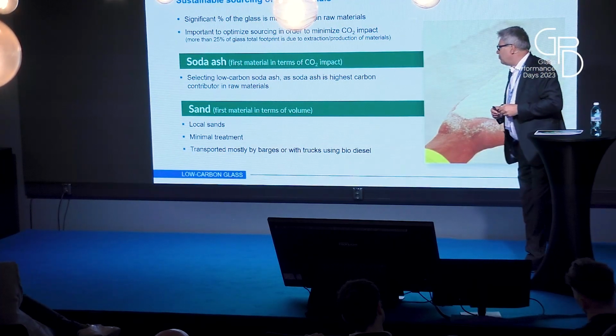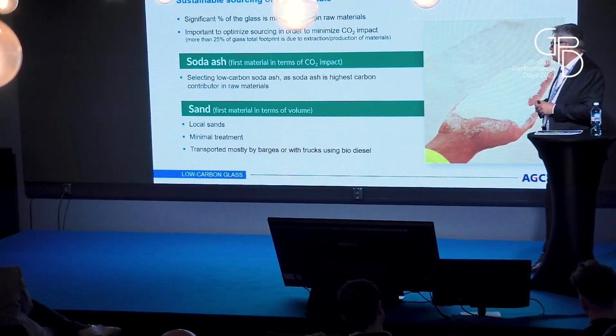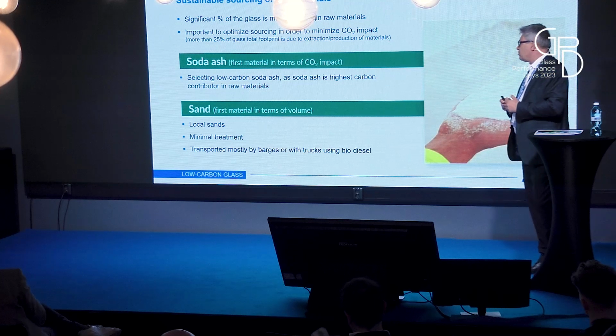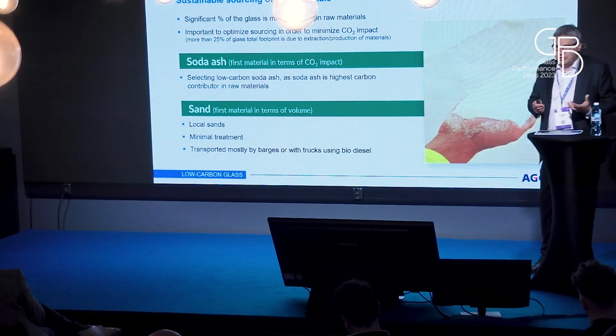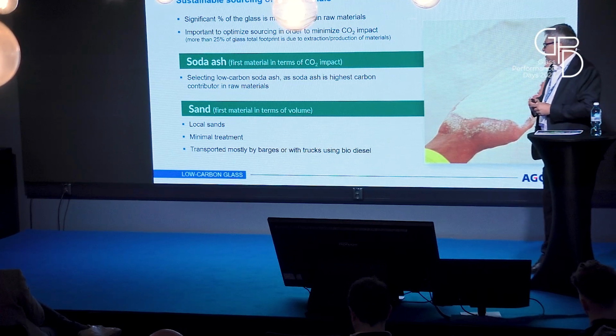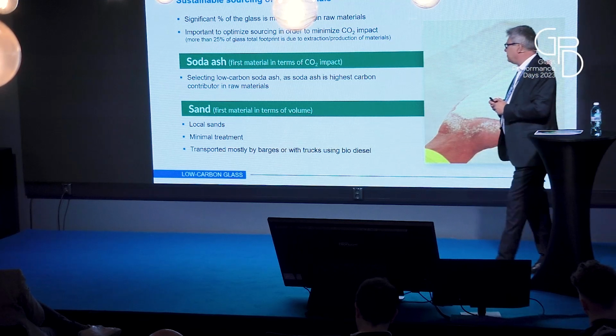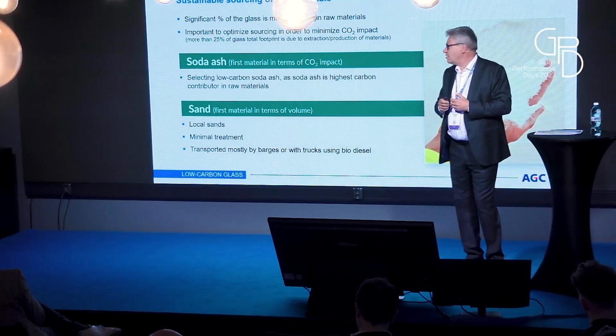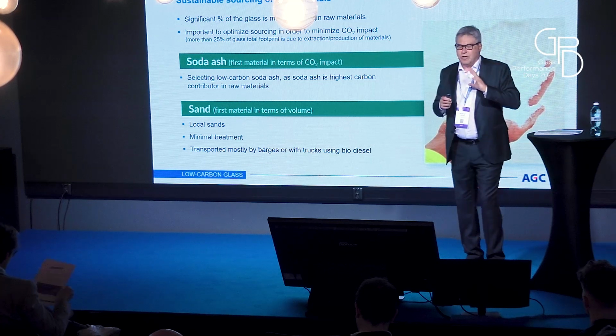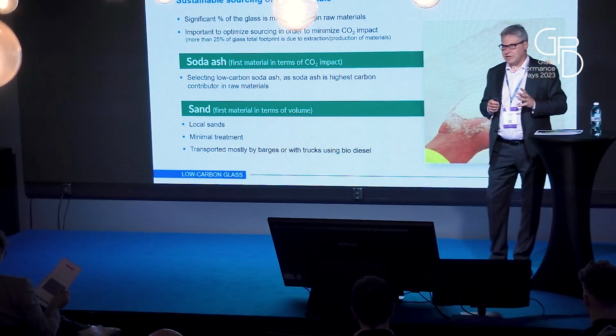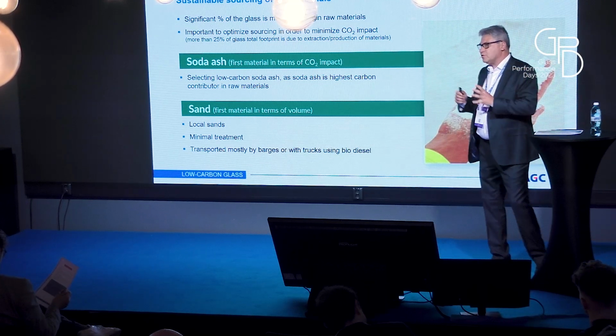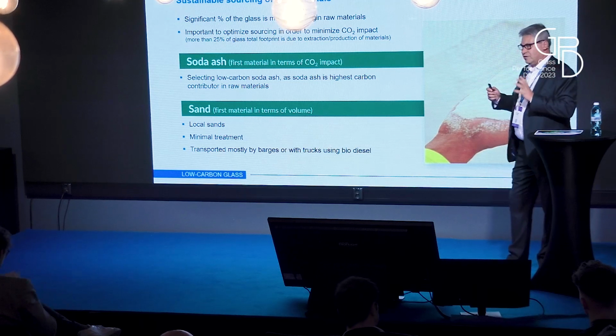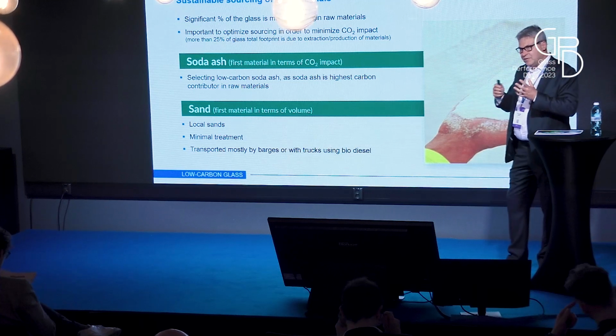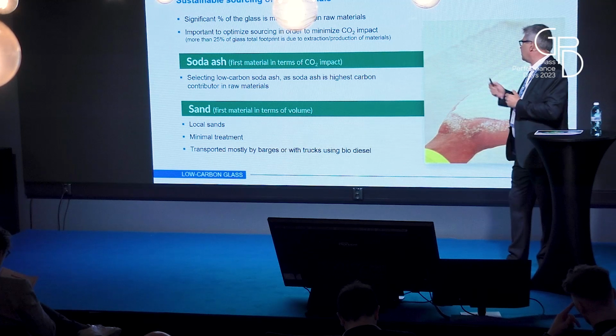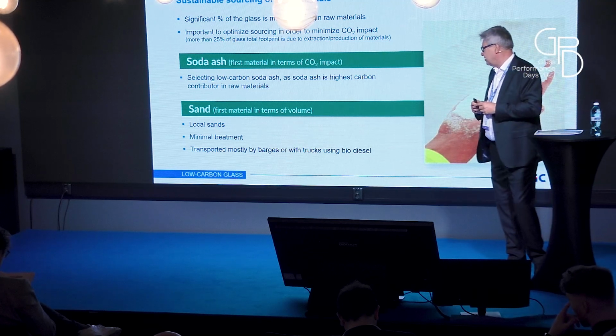So first was about the raw material. A significant percentage of the glass is made with virgin raw material at this moment. So it's important to optimize the sourcing of this raw material. We estimate that more than 25% of the total CO2 footprint of the furnace and the melting of the glass is due to the extraction and production of the raw material.